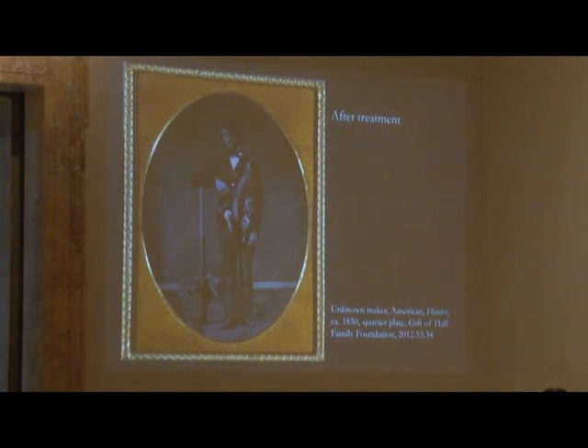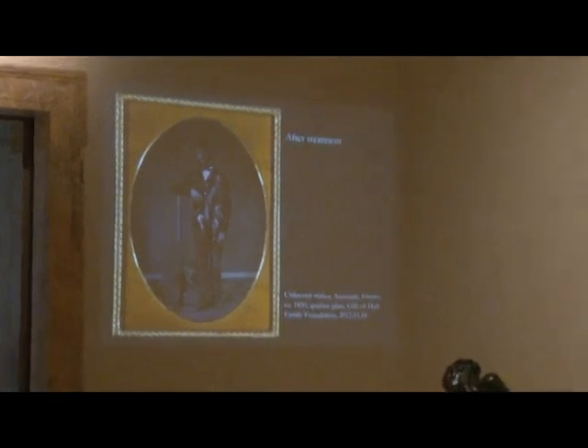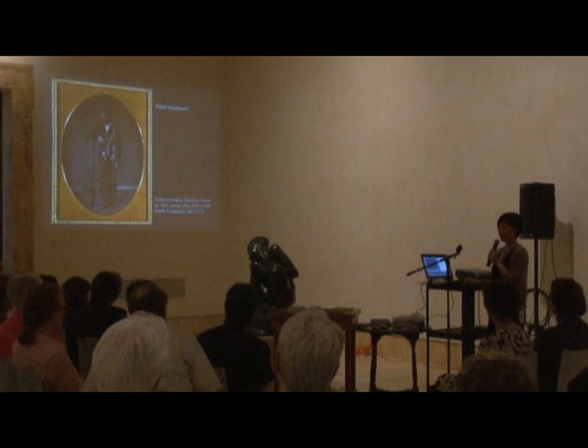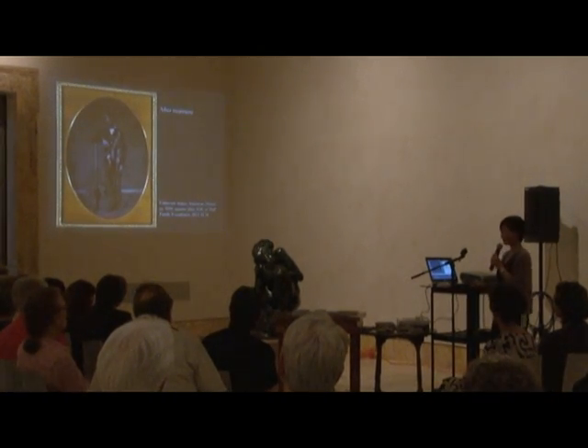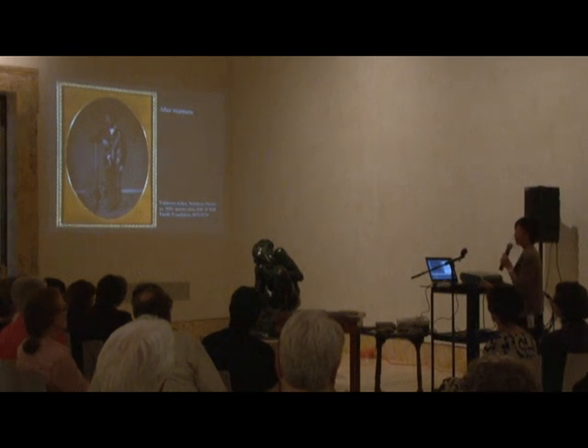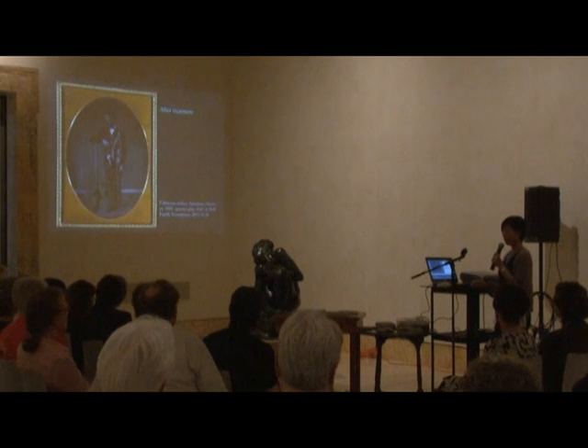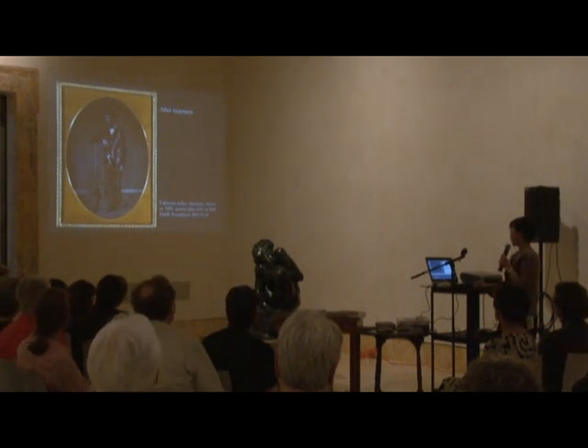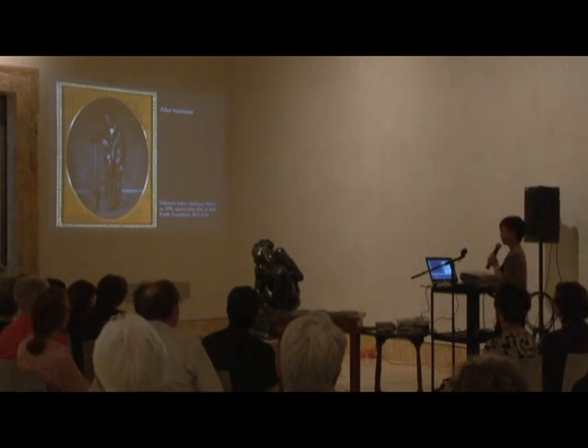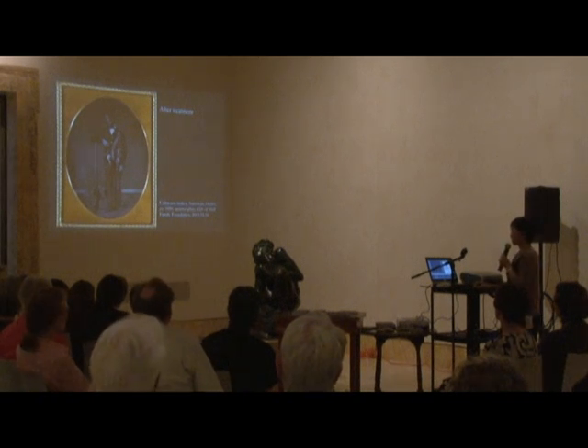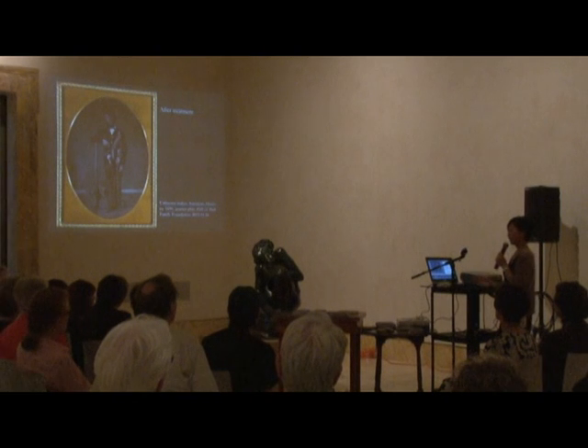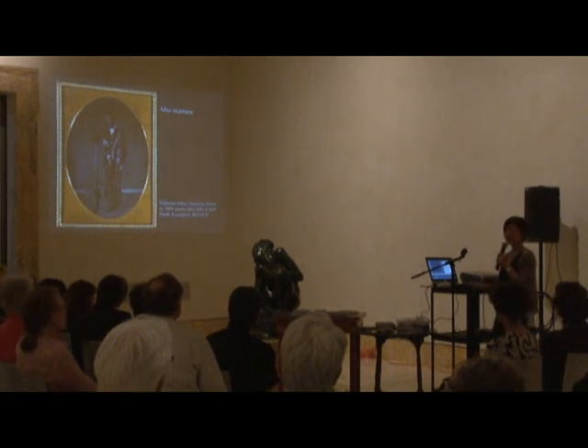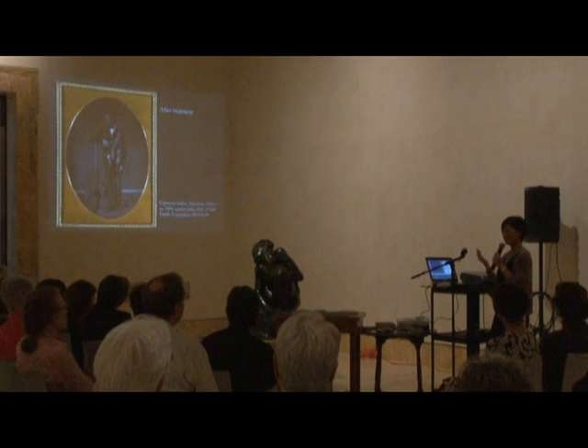Now, there are two different schools of thought about deteriorated cover glass. On one side, the cover glass is original material, and the original glass should always be kept with the plate despite its condition. The other argument, which is the one I subscribe to, is that the object's primary value is the image on the plate as it was realized by the artist. So the glass should be replaced with a new material if it's necessary to protect the image from being damaged. So when I observe glass corrosion, I change the cover glass and keep the original glass in our archive file. And another approach I will use, if the corrosion is at a really early stage, is to take it apart, wash it and dry it thoroughly, and put it back together, but reverse the orientation so the chipped side is facing out.